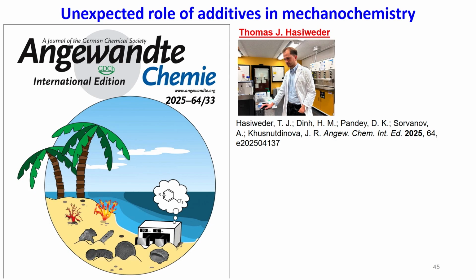We proposed some hypotheses. We proposed that iron may be involved in the reaction because we had a lot of success with iron, but we didn't fully understand the mechanism at that point. But we published our first paper where we reported this very practical and cheap protocol for mechanochemical trifluoromethylation. And Thomas created this amazing cover art for Angewandte where he depicted the ball mill sitting on an Okinawan beach surrounded by beautiful diatoms and thinking about doing trifluoromethylation.